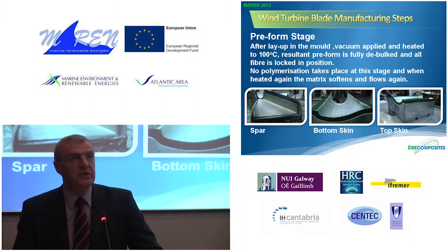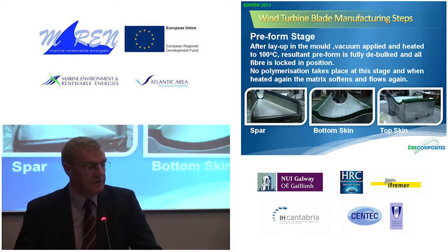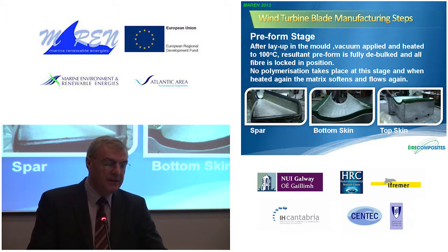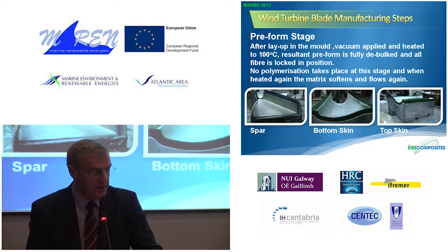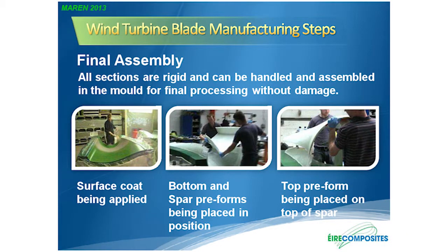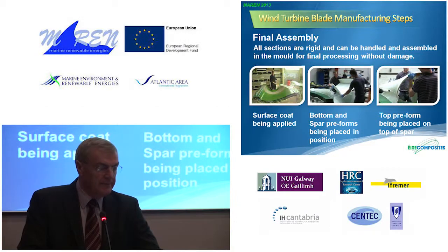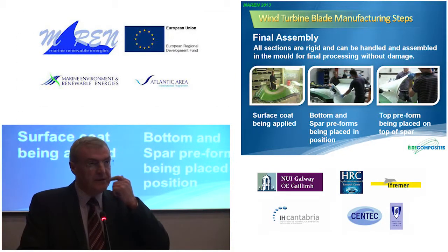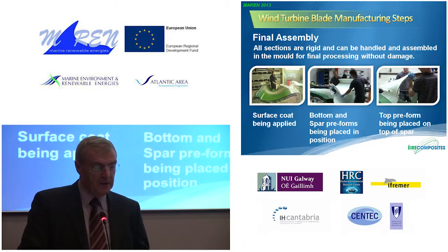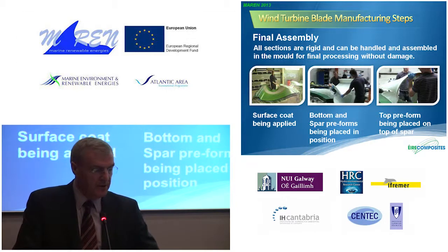However, no polymerization has taken place as yet, so that when it goes through the next stage, it melts again, and the materials will flow to fill any joints or gaps that are there in the final assembly. So the three photographs show a spar, the bottom skin of a section of a blade, and the top skin being preformed. The next stage, which is the final assembly of these parts into the mould, starts with surface coating. Again, this is optional, but if you do this, it means that the product doesn't have to be painted or sprayed afterwards. All of these materials are powder-based, and therefore you get no issues with smells or VOCs.